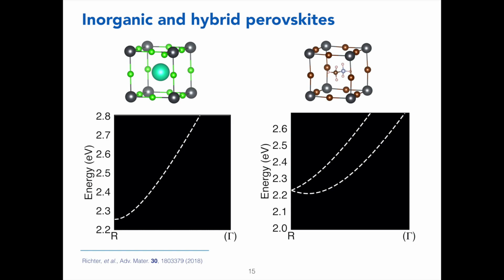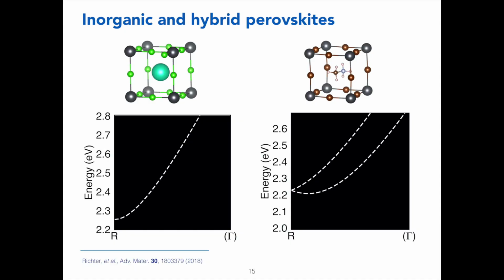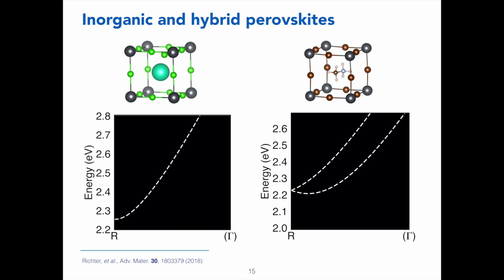It doesn't matter. So what I'm showing at the bottom are the corresponding conduction band minima along some particular path in the Brillouin zone. And what's interesting is that they look very different. The reason is that in the case of the inorganic, the cesium cation is spherically symmetric, and this band here is doubly degenerate. Electrons of opposite spin are just degenerate in energy. What happens in the hybrid case is that the methylammonium molecule has a dipole built into it, so that dipole locally breaks inversion symmetry. And because these materials contain lead, which has strong spin-orbit coupling, the combination of strong spin-orbit coupling with inversion symmetry breaking leads to a splitting of the electrons of opposite spin.